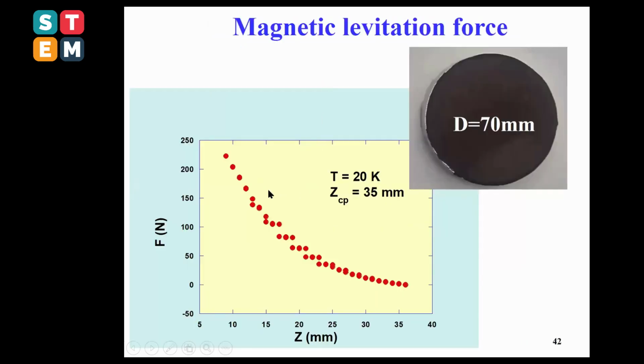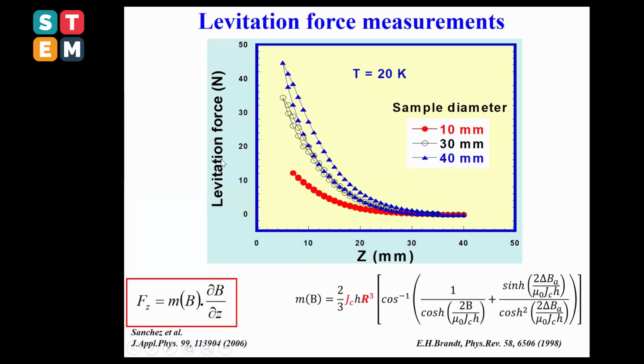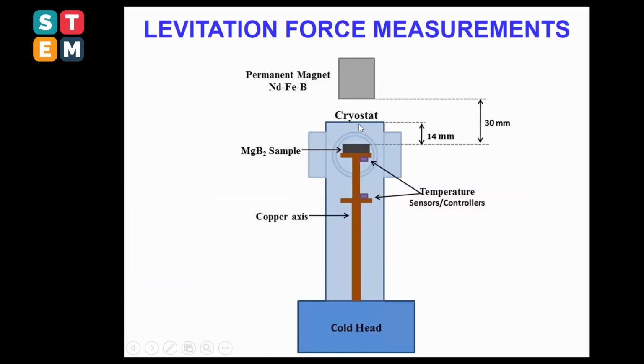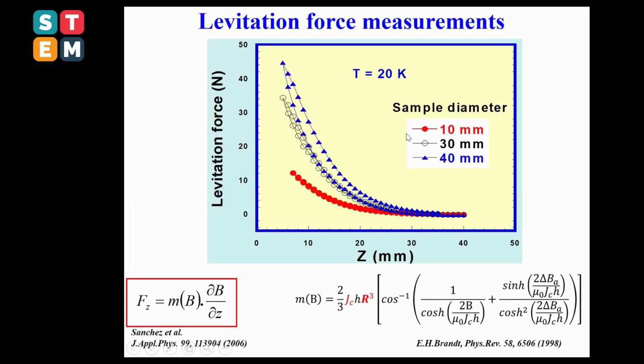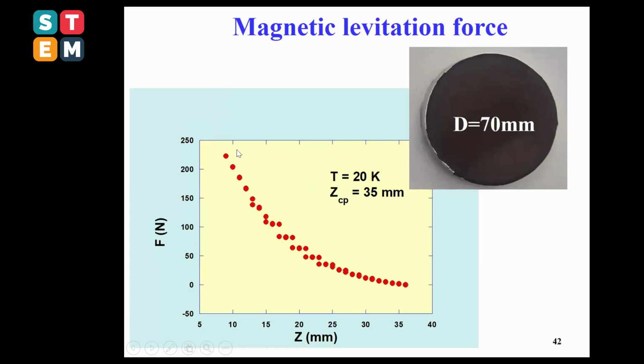Well, he was able to prepare again a big sample, 70 millimeter sample, where it was able to measure, like you can clearly observe here, a high levitation force up to 225 Newton on top of this material. But this was performed, like you can clearly observe, quite far from the surface of the sample, because in our system here you have a blue part here on top. You cannot go close to our samples. That's why you can observe here the gap is quite huge. That means if we were able to go quite close, we should be able to measure a very high levitation force on top of these samples.